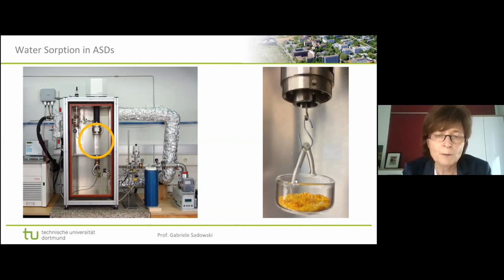So, as I said, we need this binary parameter between API and water. We could determine this, in fact, from the other side of the phase diagram, meaning dissolving the API in water. But usually, those solubilities are very, very low, and that's why they are very hard to measure. The sorption measurement is just the other side of the diagram. Here we have the solution of water in the API, and this can be measured much more precisely because the balance here is measuring 0.1 milligram. And if you make the sample big enough, you can really measure the water uptake. So this is a standard method we also use to determine the binary parameters between the API and water. It's the sorption of water in the API.